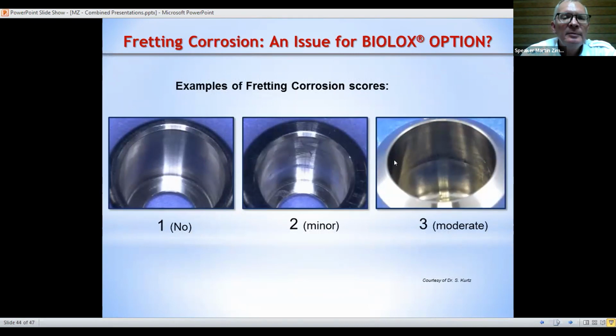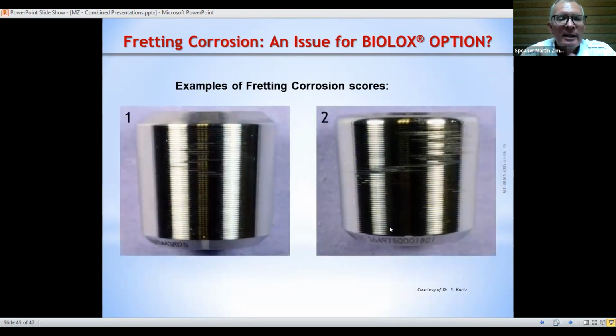Here are some examples. We see now the inside of the sleeve, which is in contact with the taper of the stem. We had some cases without any fretting corrosion, with minor fretting corrosion and moderate. And if you look at the external part of the sleeve, which is in contact with the ceramic, there were only cases of no fretting corrosion or minor fretting corrosion. There was no case of level 3 or 4 observed with ceramic ball heads.